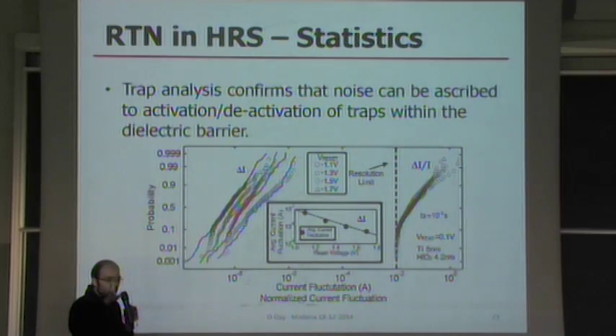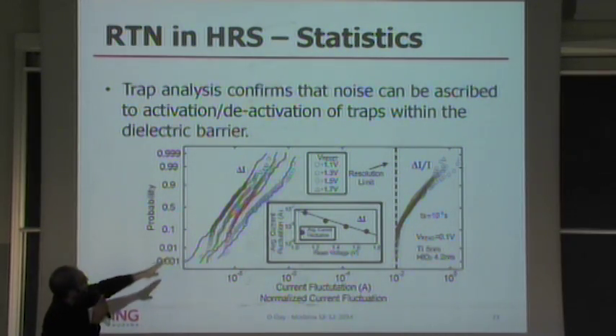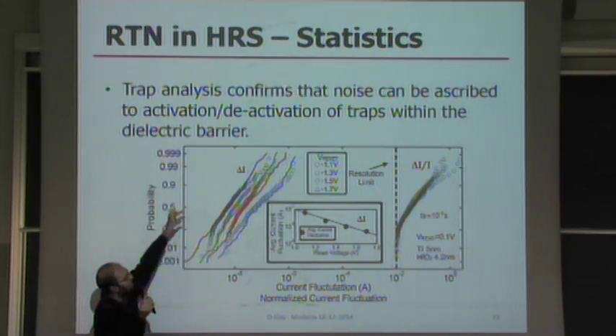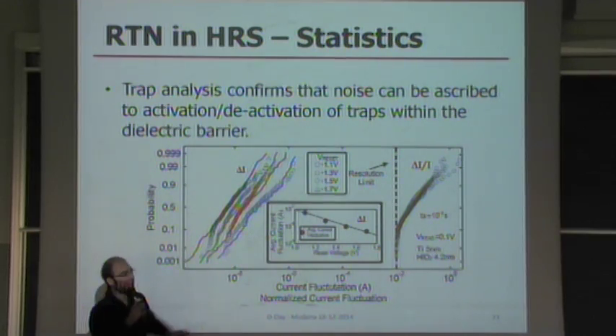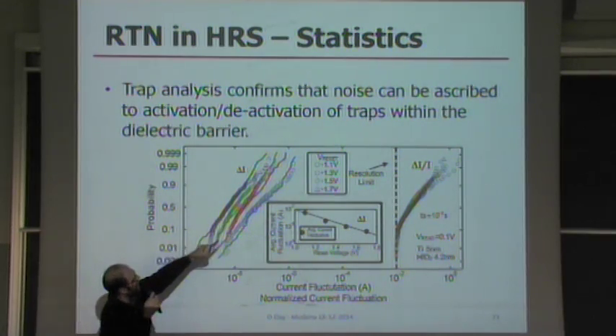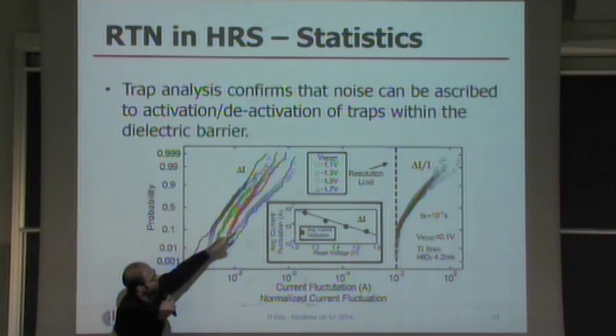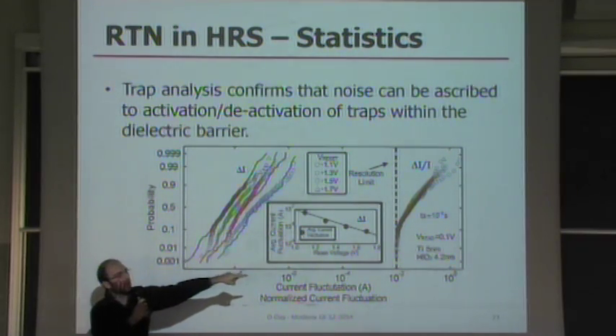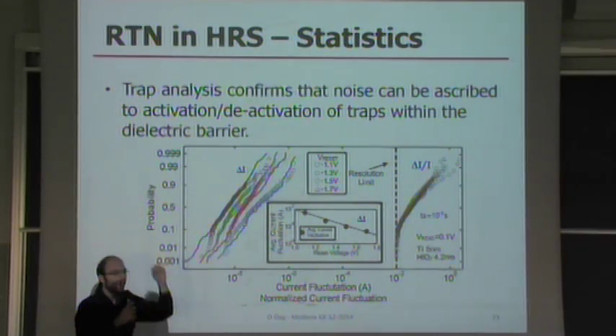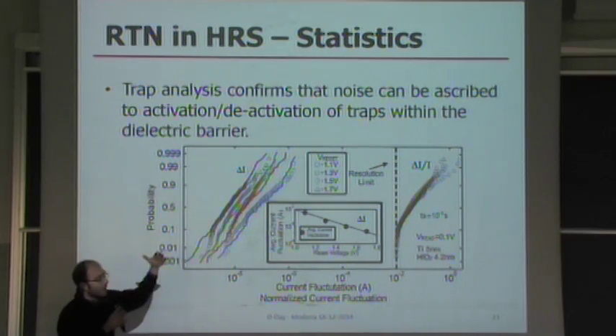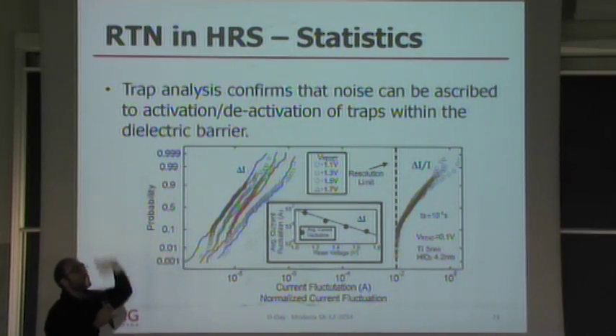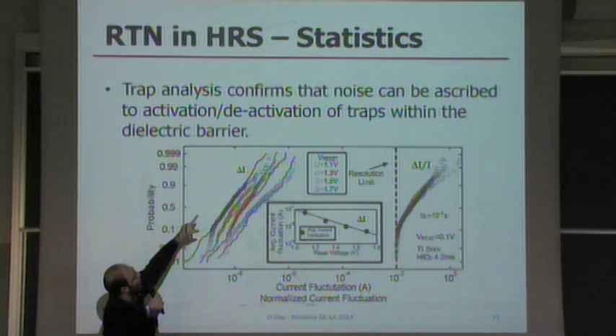And this picture, activation and deactivation, is confirmed if we look at the statistics. Here we plot the delta I of each defect that we detect in every condition. And as we can see, the average value of this distribution exponentially scales down with the reset voltage, which means, again, thicker barrier, lower general current, because the resistance exponentially increases with the barrier thickness, so the current goes down exponentially with the barrier thickness, and also the current fluctuation.